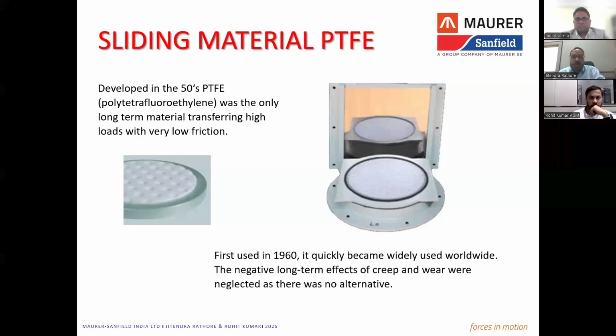This material is used because it has the lowest value of friction when checked against a polished sheet of stainless steel. Bridge bearings are also heavy, and a desirable feature is that when they move, they should offer minimum resistance to the structure while causing the movement, so that the structure doesn't get overstressed. This friction value should not be more than 3% to 5%. It is defined in the code. PTFE has dimples, and these dimples are filled with grease. So this lubricated sliding interface of PTFE and stainless steel offers a very low friction value.